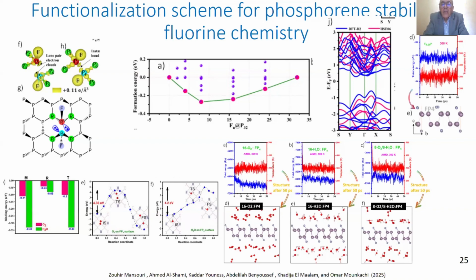Phosphorene with fluorine is protected even after a long time. And the same thing for water, the second figure, this one. It is stable at room temperature, and there is no big interaction between water and phosphorene. And even if we take both water and oxygen, there is no big interaction and no degradation of phosphorene when it is passivated with fluorine, while it is always a semiconductor.